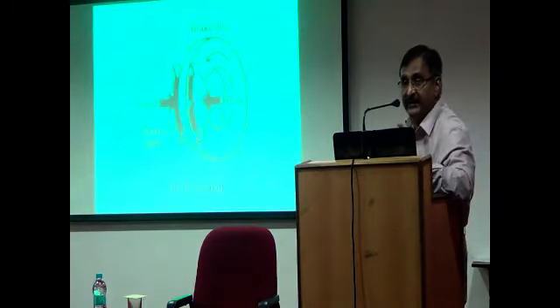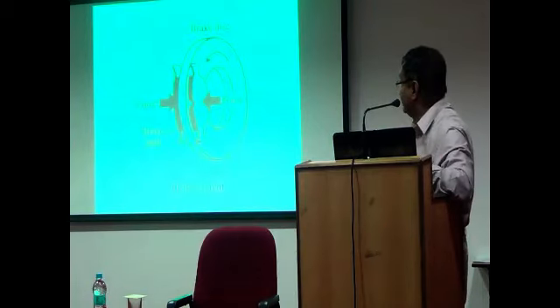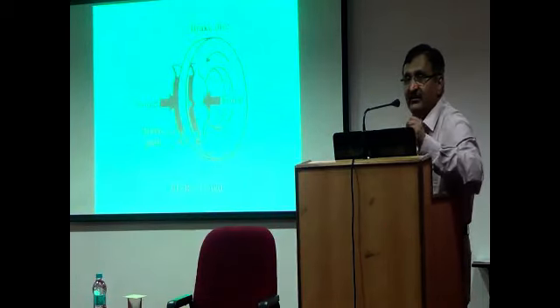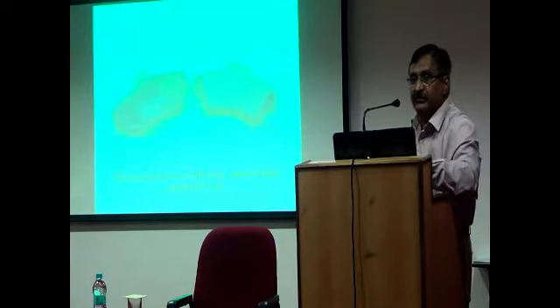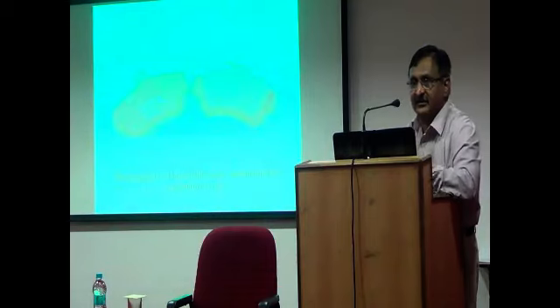So we carried out a lot of work on this, actually using the brake conditions. These are the brake pads, in the Maruti car and all. When you apply a brake, this comes in contact with the disc and stops the car. The discs that were made earlier of cast iron, we now wanted to substitute with the aluminum disc, and that's what we did, the wear test. I want to show it to you. This is the wear rate as a function of the speed. The top one is aluminum alloy, and the bottom three are the composite and the cast iron.